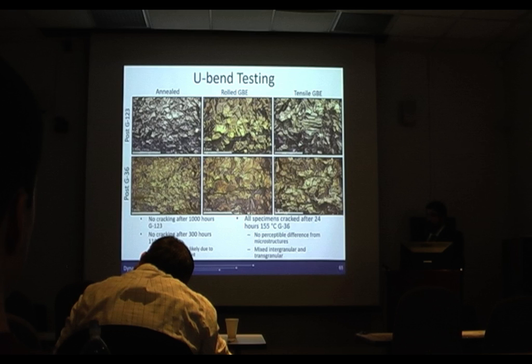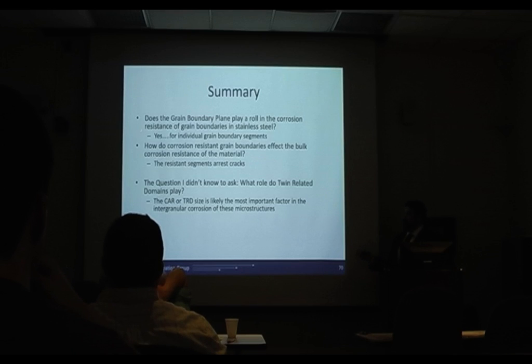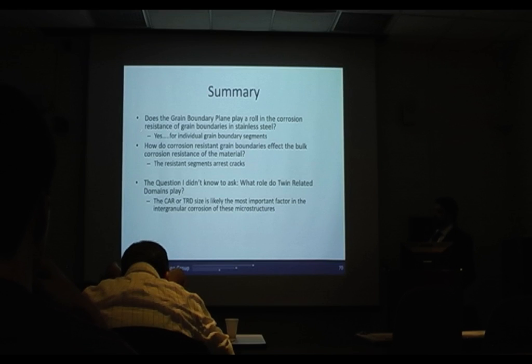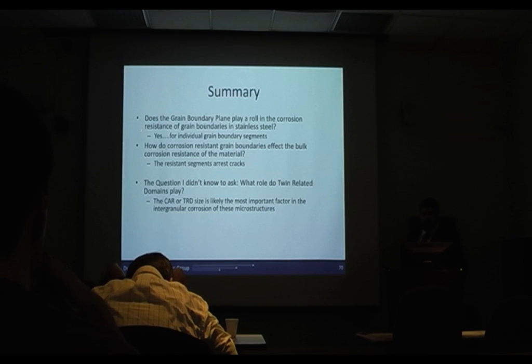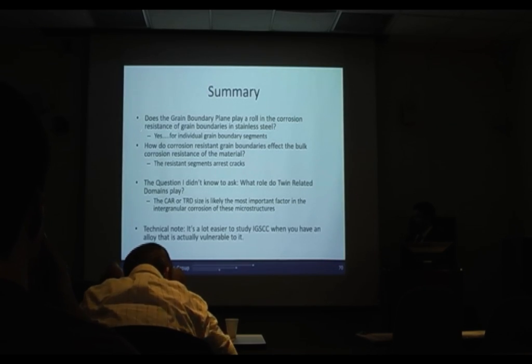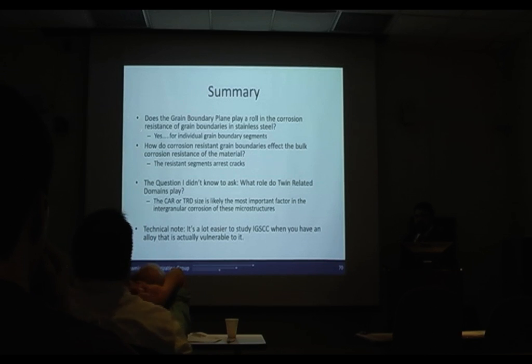And then the question that I didn't know that I should have asked was what role do twin-related domains play? And from this work, it looks like the crack arrest region or TRD size is most likely the most important factor in the intergranular corrosion of these microstructures. And a final technical note, it really is a lot easier to study IGSCC when the material will actually undergo IGSCC.